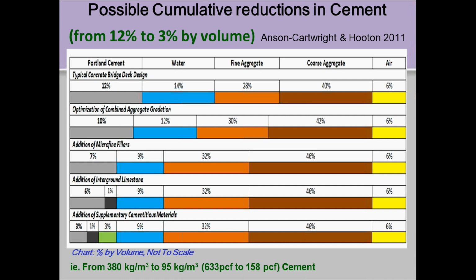potentially, and we've done this in the lab, if you look at a bar chart, I know it's difficult to see here, but the cement's the gray bar on the left, the Portland cement component on a volumetric basis. With the traditional Portland cement concrete, we might use 12% by volume Portland, and by incorporating combined aggregate gradations and fillers and interground limestone and SCMs, we can get that down to about 3%, which means you could get down to about 160 pounds per cubic foot of,